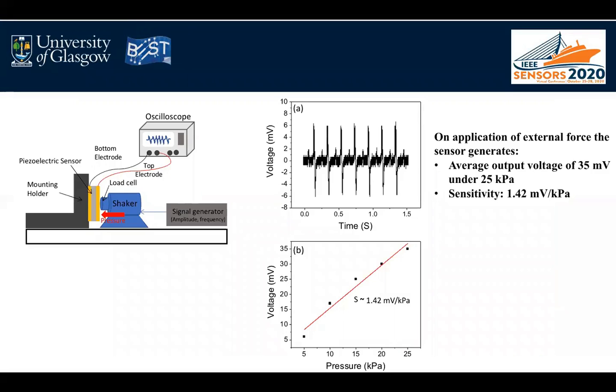And then we used a mechanical shaker that generates compressive load at a specific pressure, and the output voltage generated from the device under each applied pressure was measured using an oscilloscope. And this figure shows the output voltage from the device under the dynamic pressure of 5 kilopascal, and the voltage generation is, as you can see, quite stable and repeatable with fast response time.